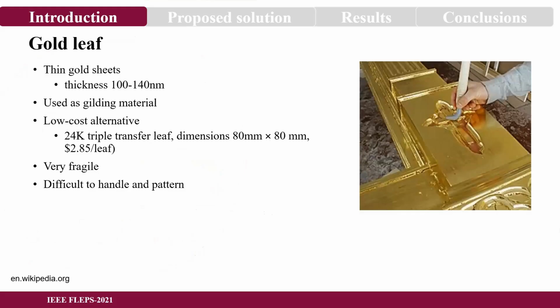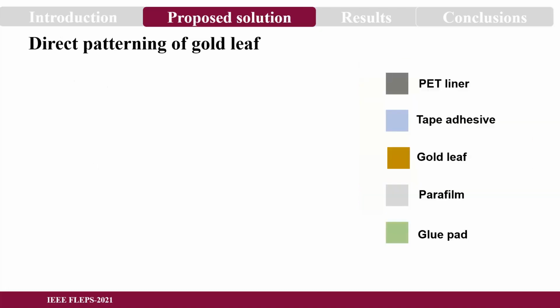So what are gold leaves? These are very thin gold sheets with a thickness of about 100 to 140 nanometers. Commercially, these gold leaves are available and used as a gilding material for different purposes like decorations, paintings, etc. This offers a low-cost alternative because an 8 centimeter by 8 centimeter sheet of gold leaf can be bought for around $3, which can give us multiple gold electrodes. But the major problem with these gold leaves is they are very fragile and very difficult to handle and directly pattern.